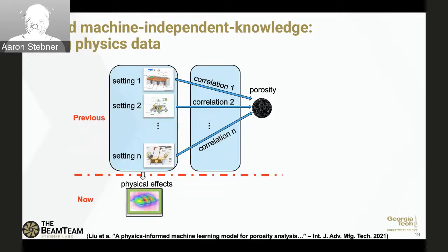We can calculate using relationships or transformations between the signals and physics. We can add data to the data set about the physics. In this case, we knew if the part was built with a certain orientation, it would have 600 layers, and another orientation, it would have 400 layers. And we knew the recoil pressure based on the position of the laser optic in the printer. If it was out at an angle, we knew the recoil pressure was much different than if it was directly under the scanner. And so we started making these calculations and augmenting the data.